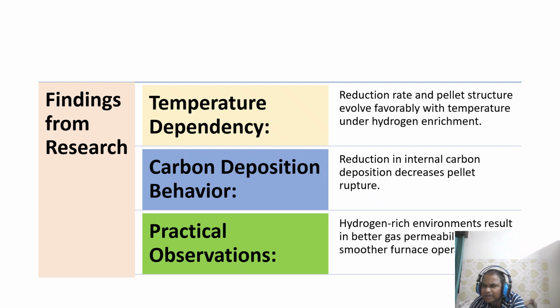Now, temperature and carbon deposition. Here is where hydrogen shines even brighter. As temperature rises, hydrogen makes the reduction process faster and cleaner. Less carbon gets stuck inside the pellet, reducing the risk of rupture. Plus, it boosts gas permeability, making furnace operations smoother than ever. Hydrogen is rewriting the rules now.